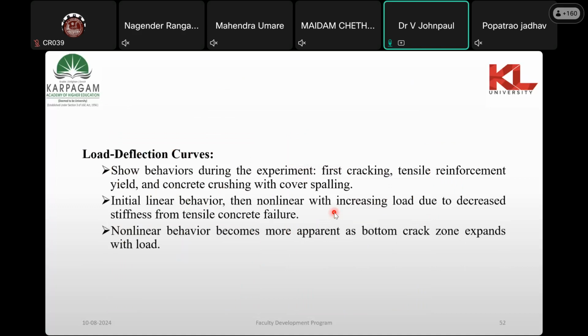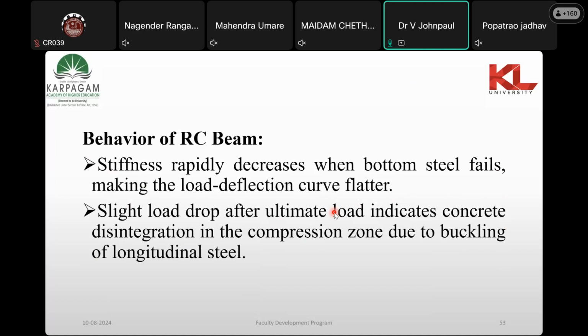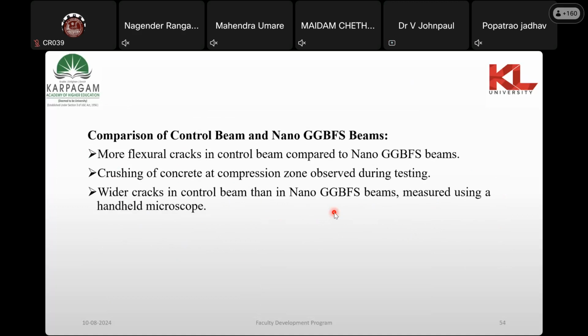It forms load deflection curves and absorbs more energy in the GGBS-based beams. More structural cracks were found in control beams compared to the nano GGBS-based beams. As the GGBS-based matrix has more bonding, it's not showing the micro cracks.